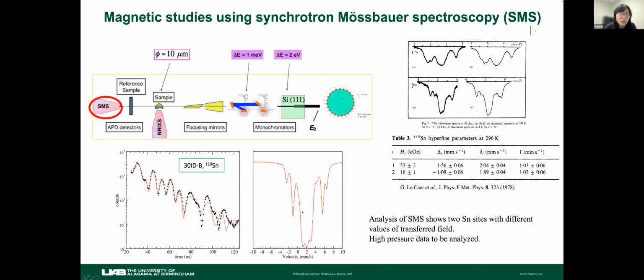Okay, we also did synchrotron Mössbauer measurements on tin-119 at different temperatures and pressure conditions. And this data here is just an example of how the tin data look. This is the enriched, fully enriched, to some extent enriched Fe3Sn2. This data was taken at room temperature, and in fitting this data, we used a 2-site model because based